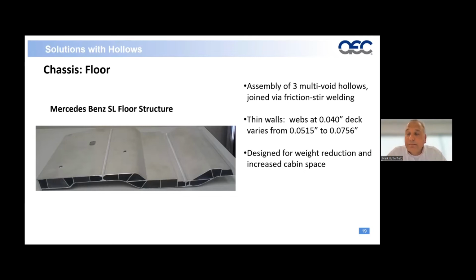Very thin walls. We got walls down to 40 thousandths and some variations from 50 to 70, but very, very thin wall capabilities. There's a misunderstanding, I think, in the industry that wall thicknesses need to be up in the 100 to 200 thousandths range. But again, that's dependent upon the type of press that's being utilized, the alloy, and the material flow paths and complexity of the hollows themselves. But this was designed for weight reduction and increased cabin space. So a good example of a large extrusion utilizing the friction stir welding process in an effective way.